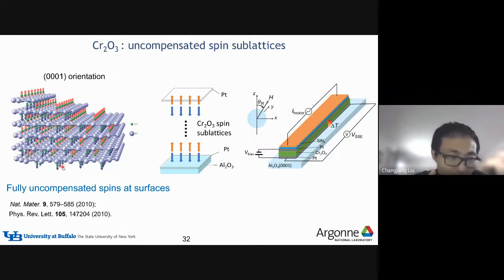simultaneously during material growth. So that means even though this is a layered structure, and because these two sublattices can only grow simultaneously, in the end, even though the bottom surface is flat with just a single sublattice with spin pointing down, and even though the top surface is rough, still the top sublattice can be just the other sublattice pointing in the opposite way than the sublattice at the bottom. So this means the top and bottom surfaces belong to two different sublattices of this chromium oxide.